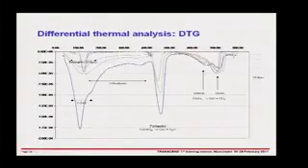You can see that you have another effect of the amount of this sample. So if we look at this calcium hydroxide peak here, you can see what's the same is the onset of that reaction. But the actual position of the peak depends on the amount. So when we have a very small amount, the peak is here. When we have a larger amount, it occurs much later on. And that's normal, because you're heating at a defined rate. The phase starts to decompose at a given temperature, but the length of the period of temperature over which it decomposes will depend on the amount. So all of these things are a little bit of precision that you need to be aware about.